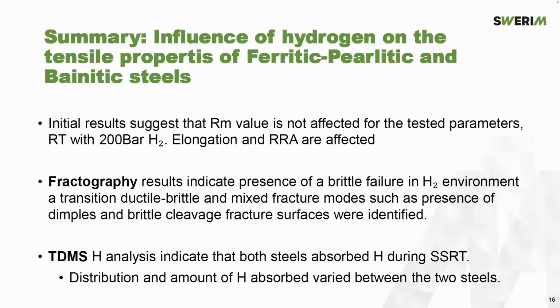So we can say that the UTS is not affected in these materials, but we have a reduction of elongation and reduction of area under hydrogen environment. Fractography says that we have some presence of brittle failure in hydrogen environment, and TDS suggests that there is a different distribution of hydrogen inside of the material in different trapping sites.